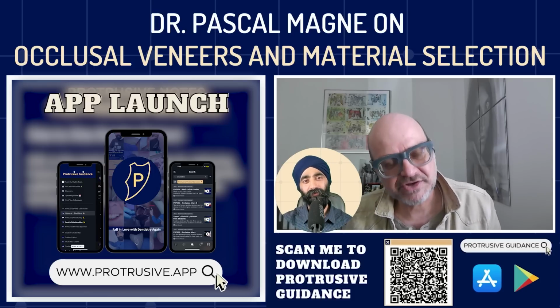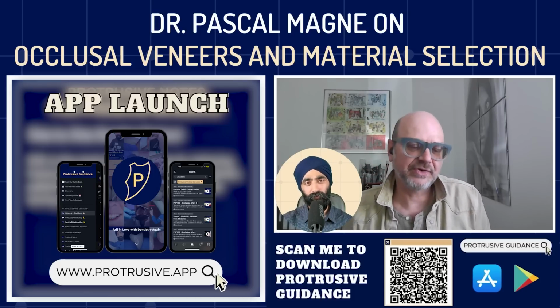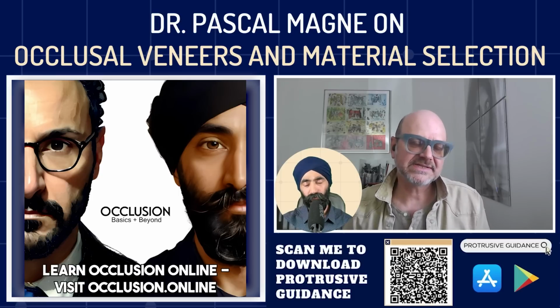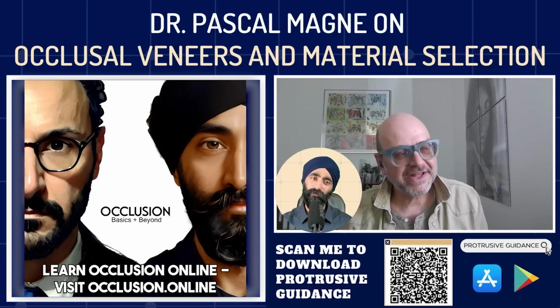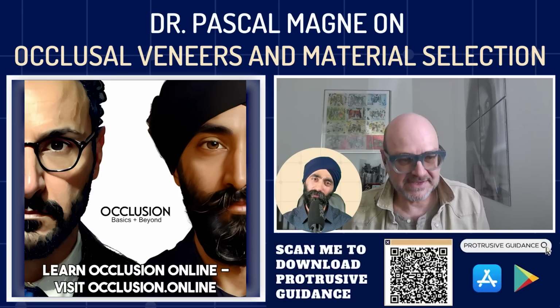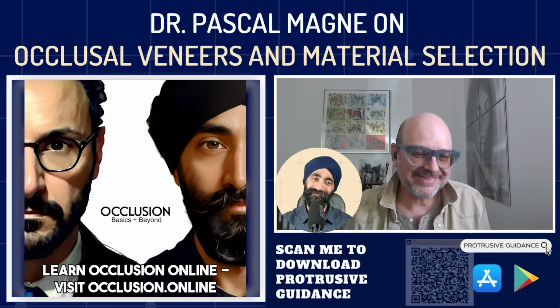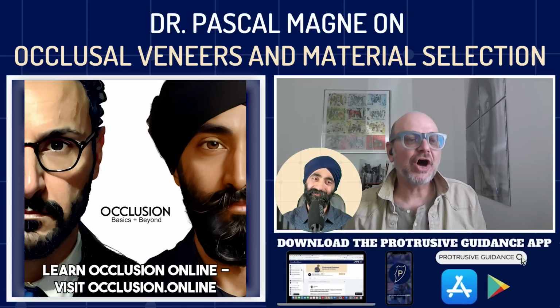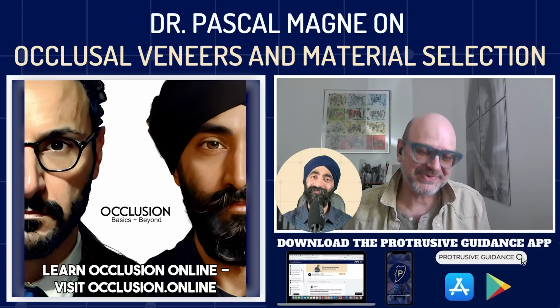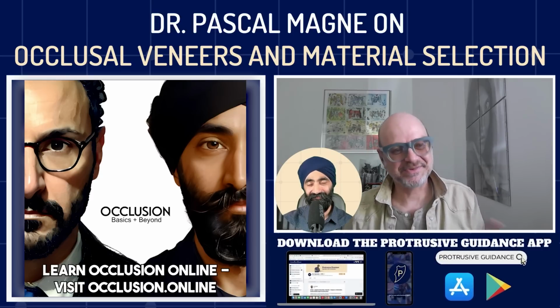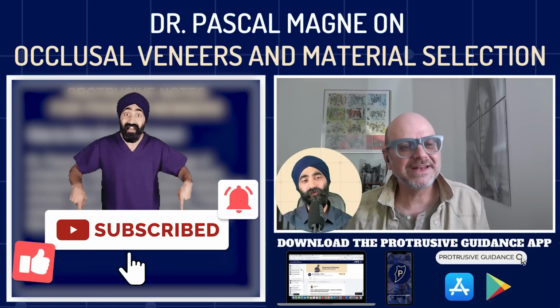And you have less risk of breaking that restoration during the try-in. So that's important. But in general, the beauty is with composite resins, if the bite is a little bit off, it's so much easier to adjust than with lithium disilicate, or even worse with zirconia. So it's not going to be that big of a deal if it's a little bit off with composites.